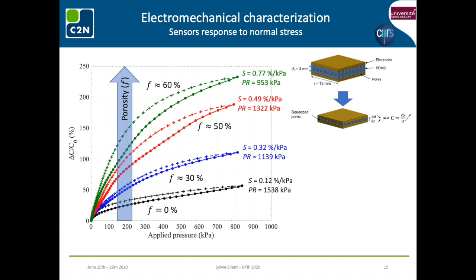Here are some examples of load and release characterization curves for sensors made with 3 mm thick PDMS layers, either bulk or scaffold. In this example, we can clearly see the influence of the porosity on the sensor's performance. Indeed, the sensitivity of the sensors significantly increases from 0% porosity in black to 60% porosity in green, while the pressure range decreases accordingly.